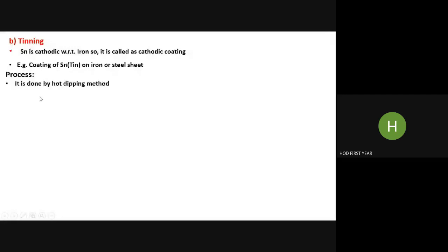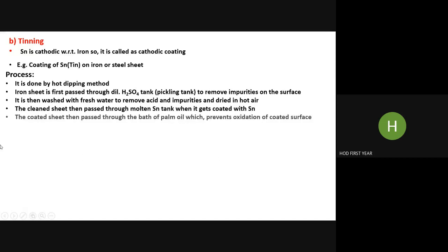The same method is used, hot dipping: simply dipping that steel sheet or any other article into molten tin. First the iron sheet is passed through a dilute H2SO4 tank, the pickling process, to remove impurities on the surface, then washed with water to remove acid, and then dried. Same steps, preparation of surface, same steps we follow. Then the clean sheet is passed through a molten tin tank, where it gets coated with tin.